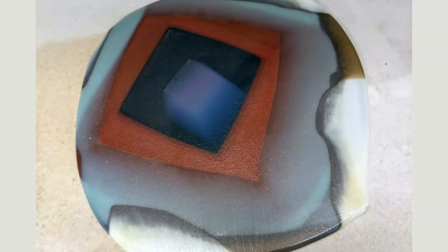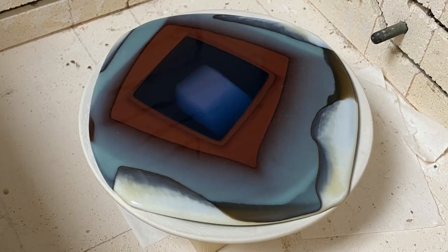When the piece emerges from the kiln, it may have some kiln wash residue or even stuck-on kiln wash. This can be easily cleaned off, either by hand or by sandblasting. If you want your finished piece to have a matte rather than a shiny final appearance, you can just clean it and then go ahead and slump. But if you prefer a shinier appearance, then you'll want to clean the piece, fire polish, and then slump.